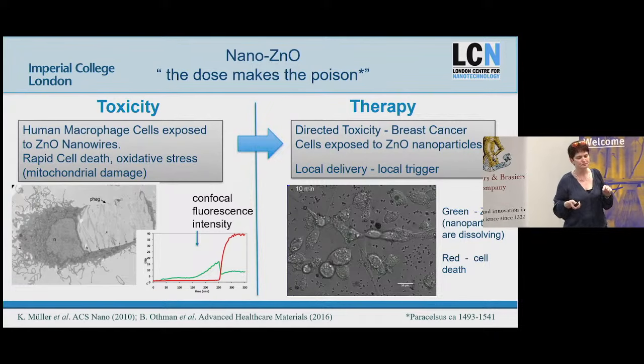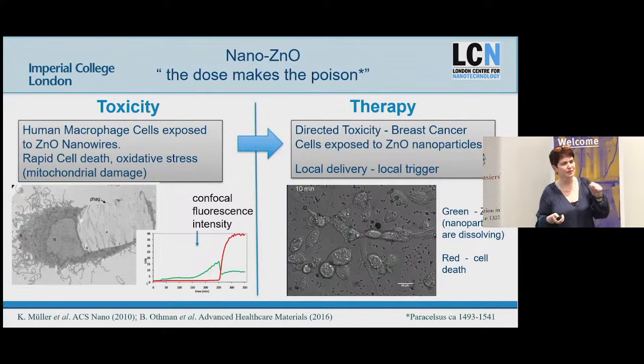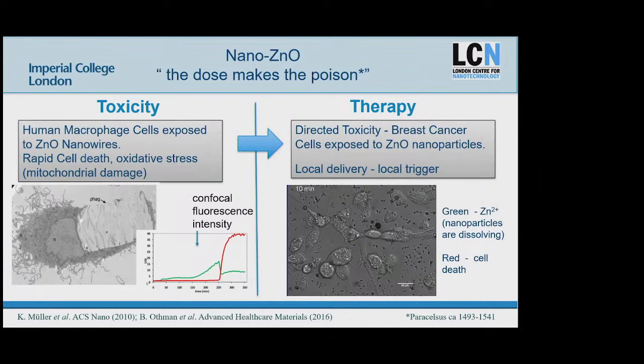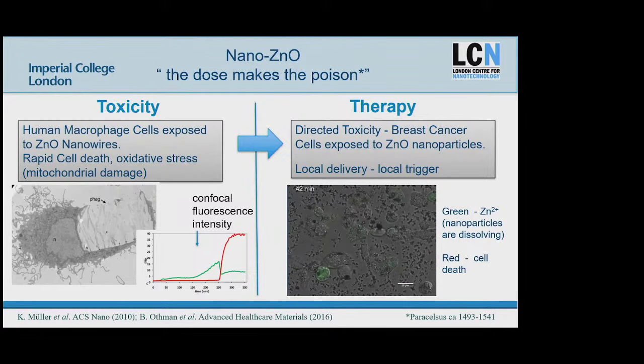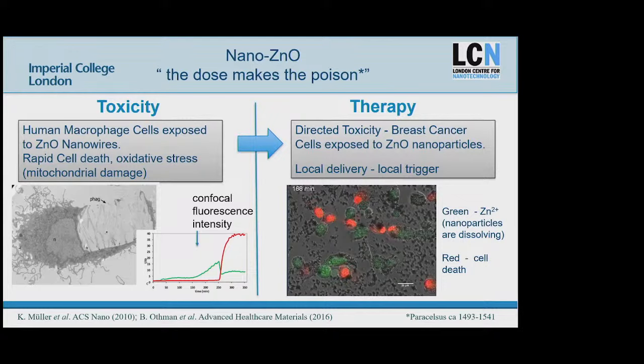Then we thought, actually, if we can make things die very locally, there's a toxicity issue, but potentially there's a therapy issue. So what you're going to see here is we're still delivering zinc nanoparticles to cells, but now these are breast cancer cells. And we've put a chemistry on the surface of our nanoparticles to specifically target those cells. And it turns out cancer cells require a lower dose than our immune system. So you found an envelope that's not toxic to the bulk host, but locally delivered, can deliver this toxicity.